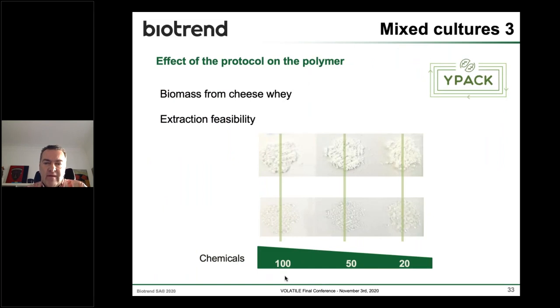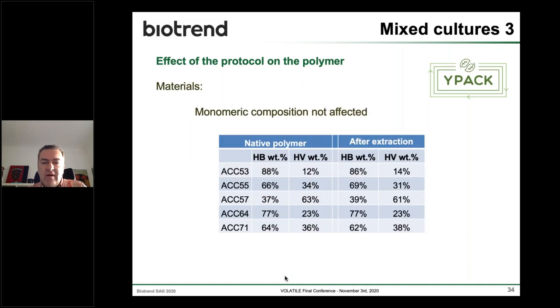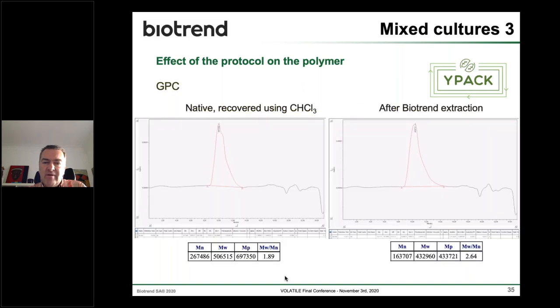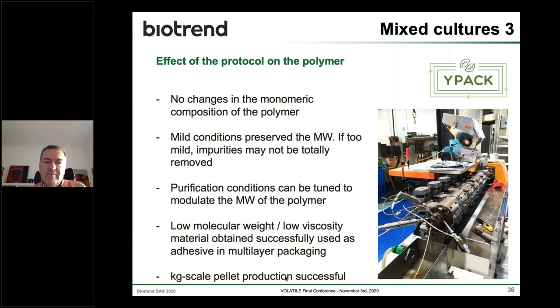And this is another example from the cheese whey process. The reduction of chemicals was quite substantial from the benchmark conditions to the optimized conditions. This is very important from the cost point of view and also our sustainability point of view. The monomeric composition of the polymer was preserved. It means that the side chains of the monomers were not affected by the digestion process, and we preserved quite nicely the native properties of the polymer. And also in terms of molecular weight, you can see the size exclusion chromatograms are very comparable from the native polymer and the polymer purified at Biotrend.